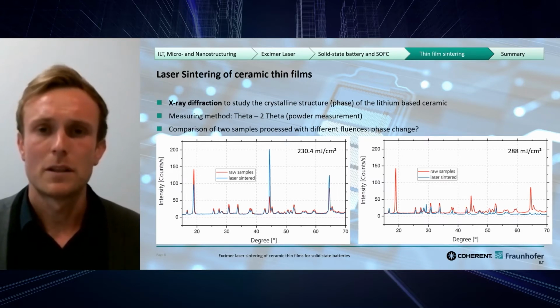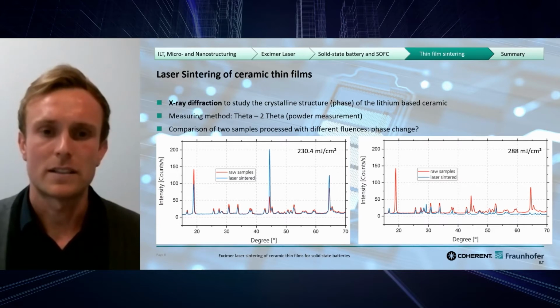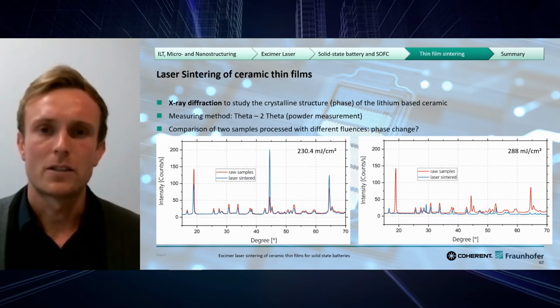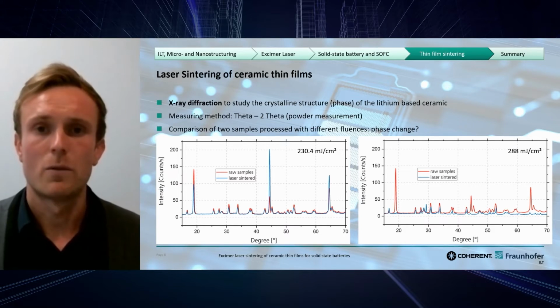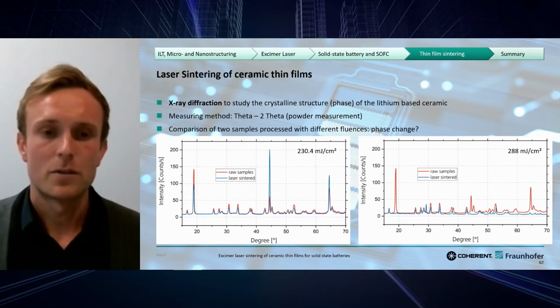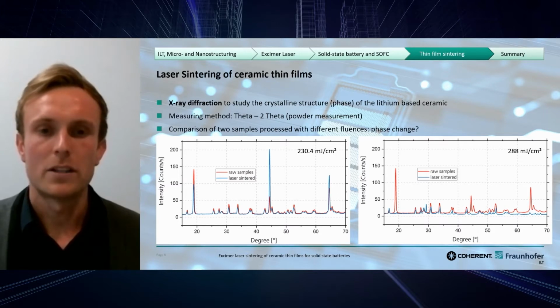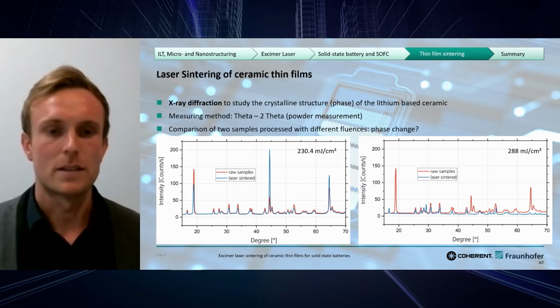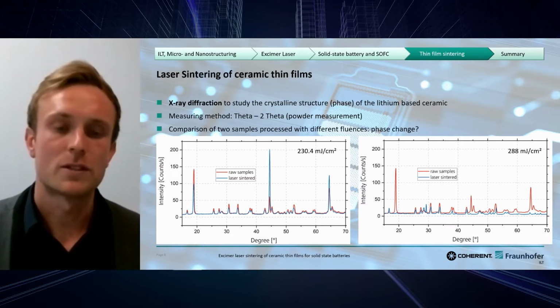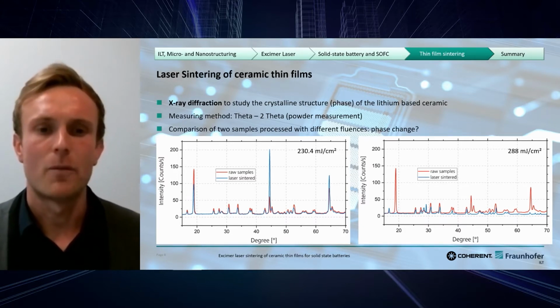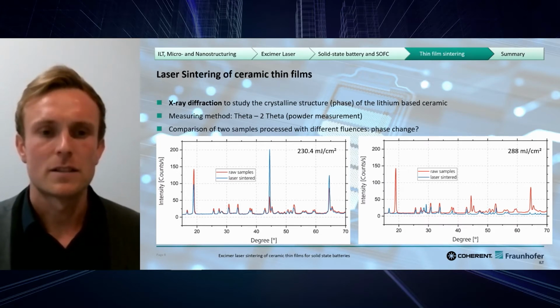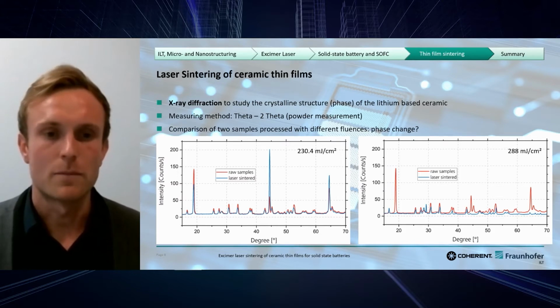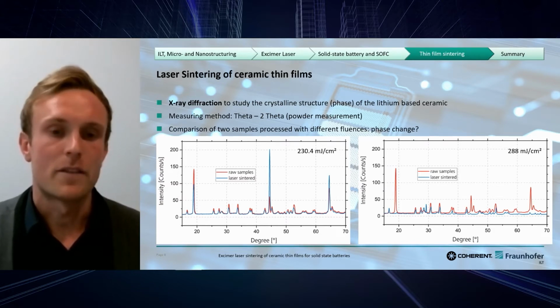One possibility to analyze that is looking at the crystalline structure and comparing the crystalline structure of a sintered material with the raw material. The sintered materials are the blue graphs, and the raw material are the red lines. And we compare here two different samples with two different fluences. On the left-hand side, where a sintering process was carried out, we can see that the phase stays the same. So the positions of the reflections are at the same angles.